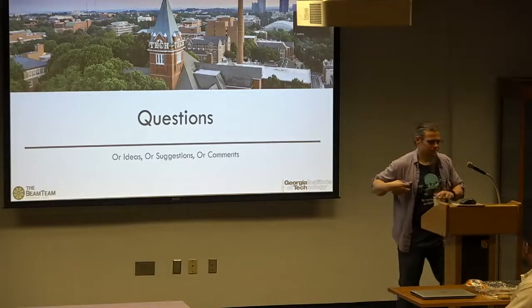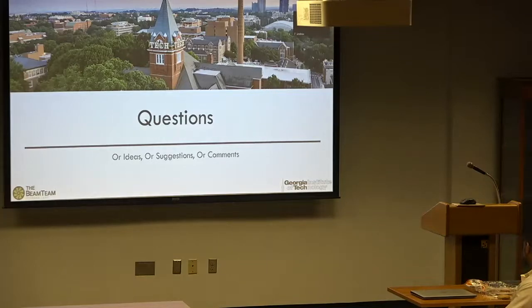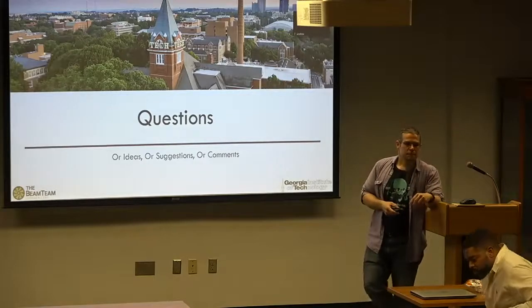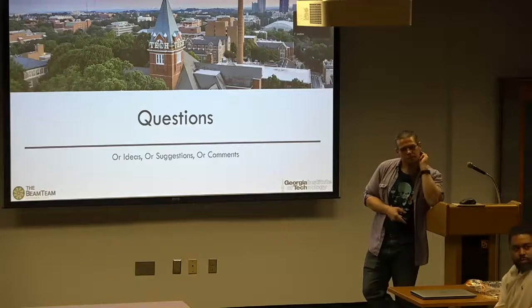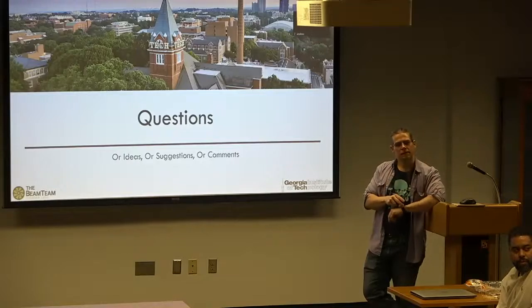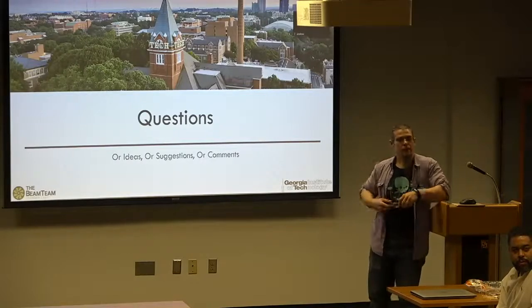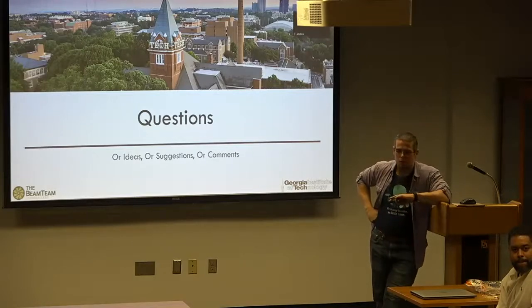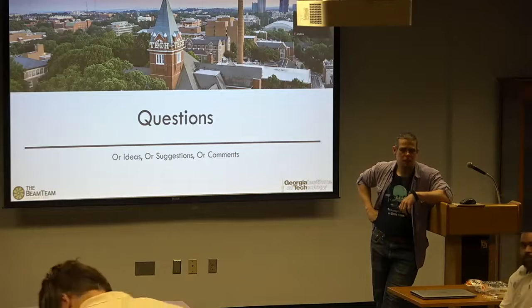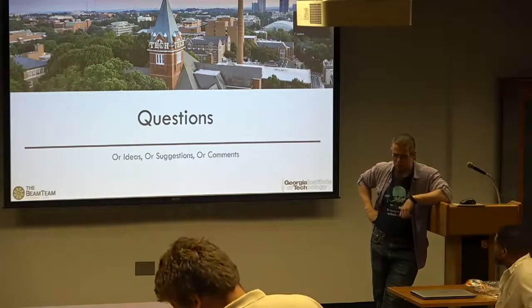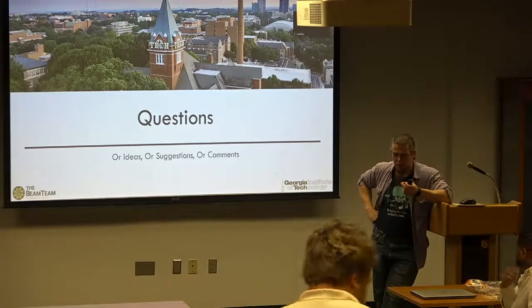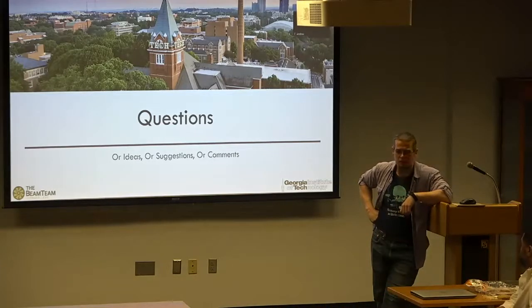Using the tomography, whether X-ray or the magnetic fields, is it possible to control or detect faults in situ and in real time? Because you are getting an image, and to detect and give feedback, you have to do some image processing. So for XCT, no, there's just not a chance. When I did dwell fatigue studies with these little 1 millimeter diameter samples, it was taking us anywhere from 8 to 64 hours to get a scan, depending on the resolution we wanted. That doesn't give you real-time feedback.